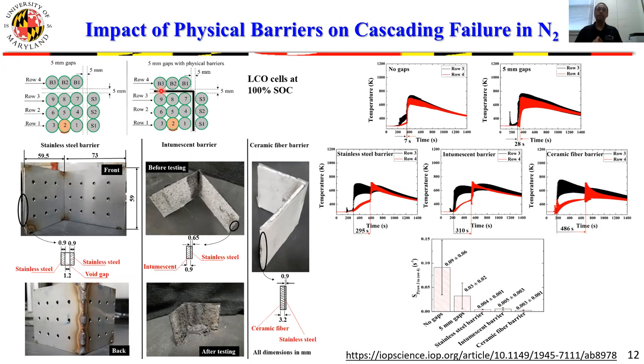So we did these experiments in the same tunnel setup. We just slightly redesigned the holder to enable a different battery module design. And what we found was that air gaps, even 5 millimeter gaps, which is about as large as you can afford in those densely packed modules, were ineffective. You do end up increasing the timing between the successive thermal runaways in a row by about 20 seconds, but it's nowhere near significant enough to affect the dynamics of the overall process.